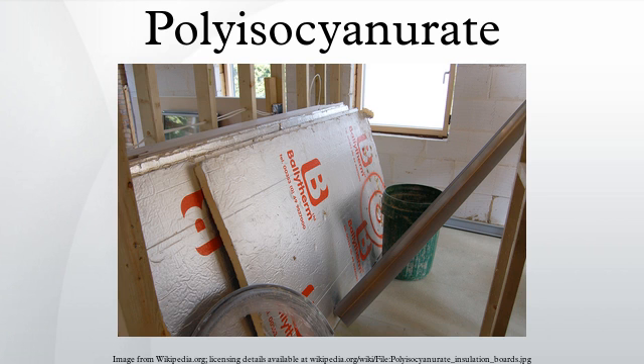Effectiveness of the insulation of a building envelope can be compromised by gaps resulting from shrinkage of individual panels. Manufacturing criteria require that shrinkage be limited to less than 1%. Even when shrinkage is limited to substantially less than this limit, the resulting gaps around the perimeter of each panel can reduce insulation effectiveness, especially if the panels are assumed to provide a vapor infiltration barrier. Multiple layers with staggered joints, ship-lap, or tongue and groove joints greatly reduce these problems.